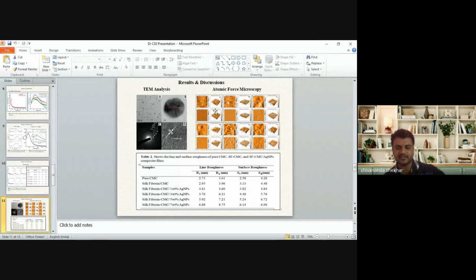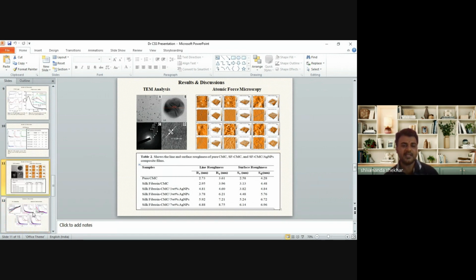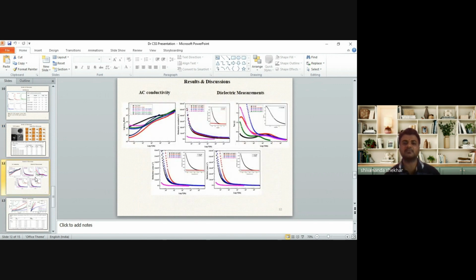And also we have calculated the line roughness and surface roughness of the composite films, and we have evaluated and tabulated them here. This is the line roughness and the surface roughness of the pure film and its composites. Then we have done some AC conductivity and dielectric property studies.